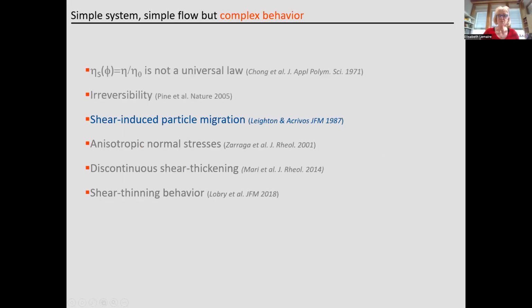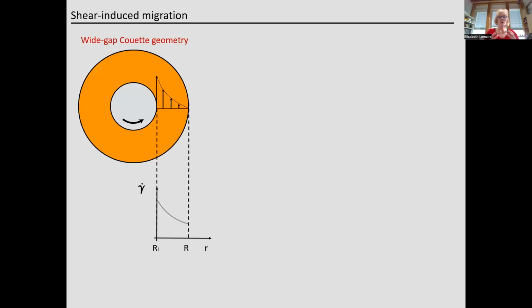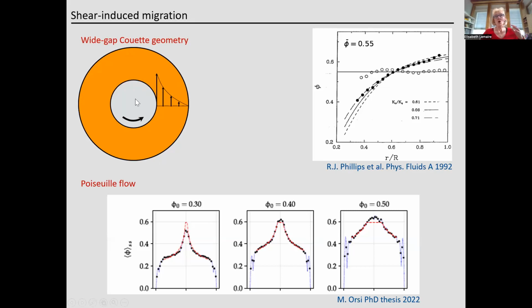So that means that if you shear concentrated suspension with a shear rate that is not spatially constant, then the diffusion coefficient varies spatially, and this spatial variation of the diffusion coefficient leads to shear-induced particle migration, and the particles migrate toward the regions where the shear rate is the lowest. So here, for instance, in a wide gap Couette geometry, the shear rate is higher near the inner cylinder than near the outer cylinder. Then particles tend to migrate outward, and it's what you can see here on this experimental curve obtained by Phillips a long time ago.